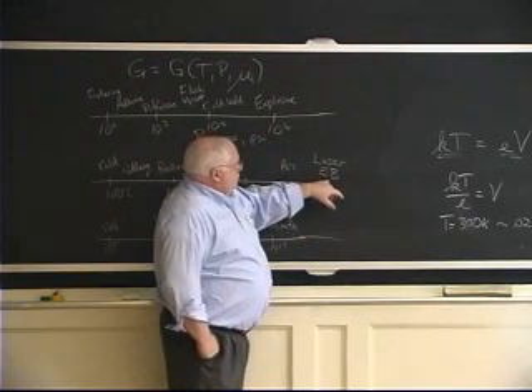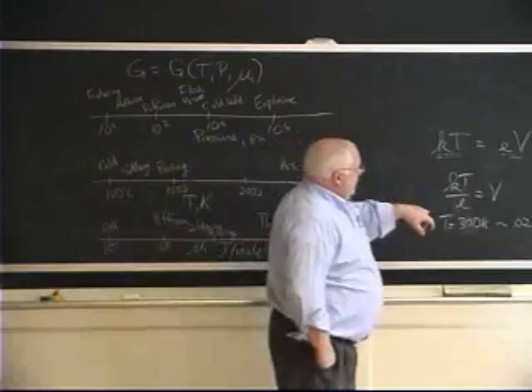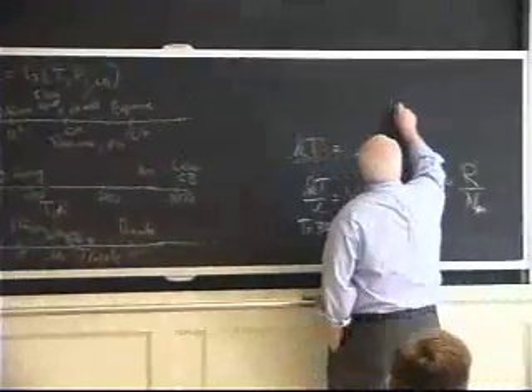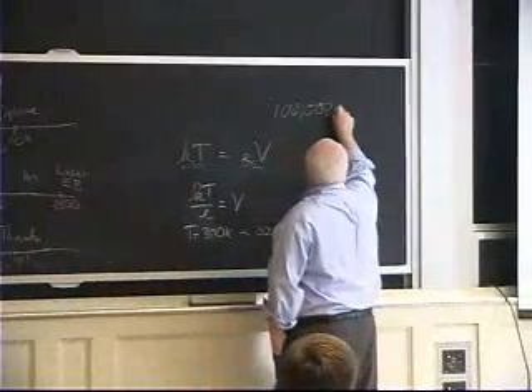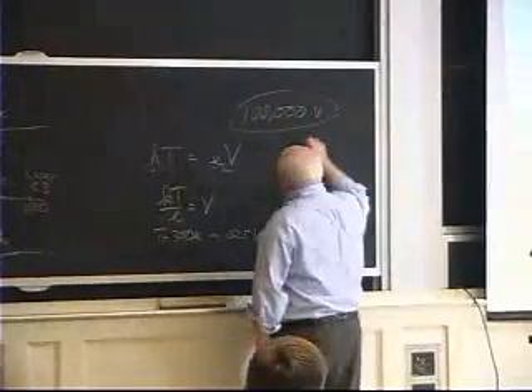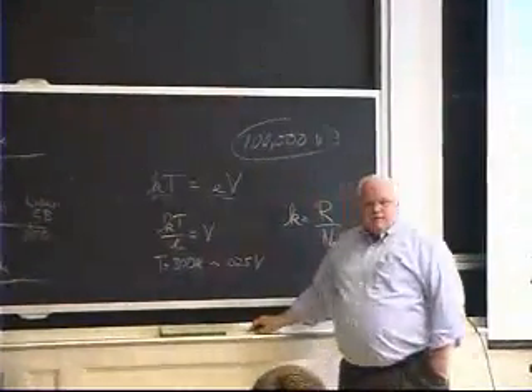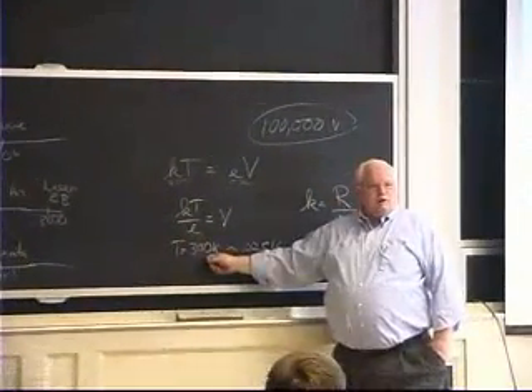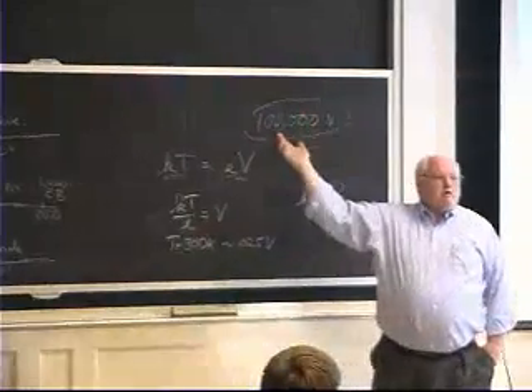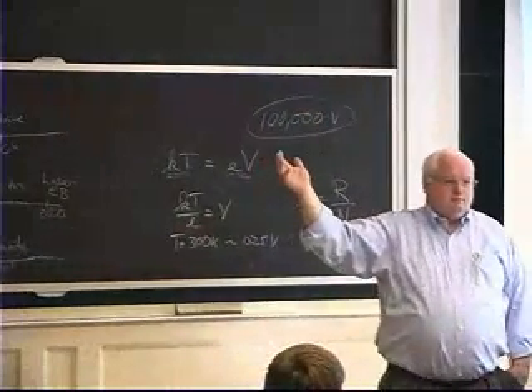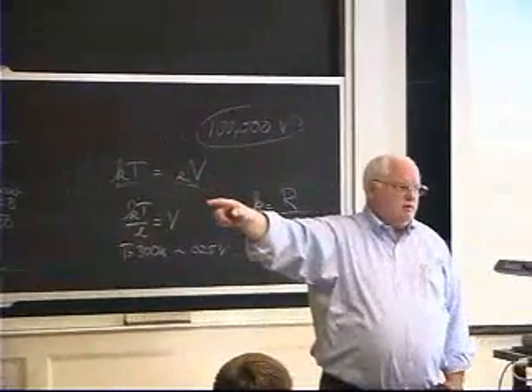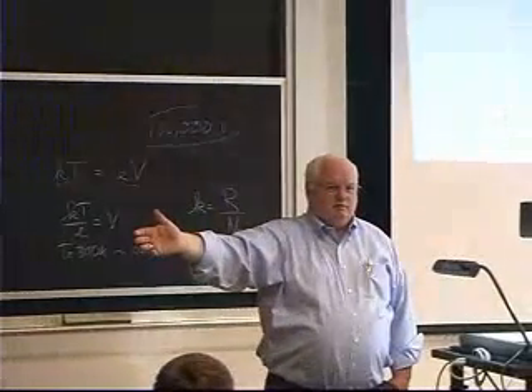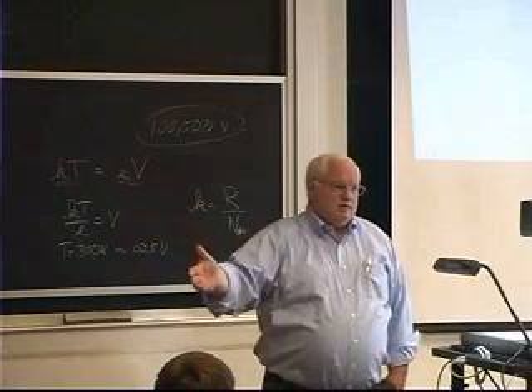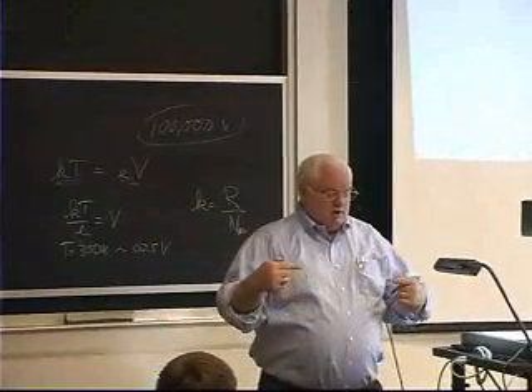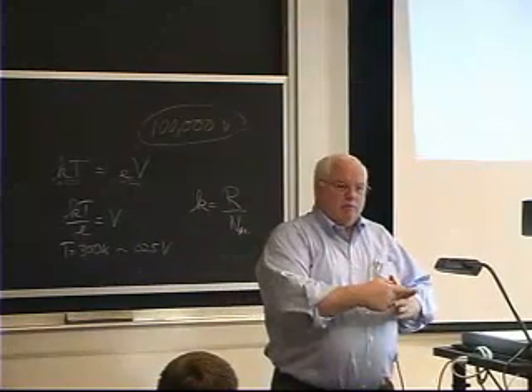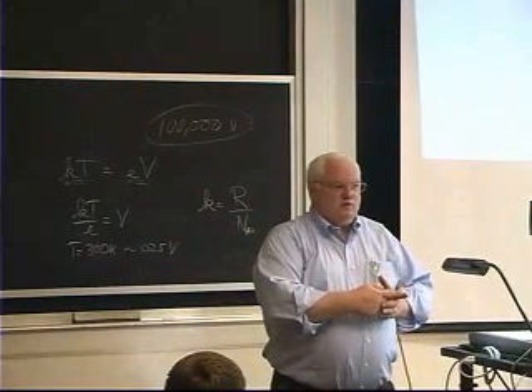Anyway, lasers and electron beam. Well, an electron beam has a voltage on the order of, let's say, 100,000 volts. If you take that 100,000 volts and you take the same ratio, and you figure out what temperature in Kelvin that is, you're going to get some sort of 100 million degrees. So an electron beam has an effective temperature of 100 million degrees. How useful is that? It's next to worthless to even say it, because that electron, when it hits an atom, doesn't transfer very much energy.